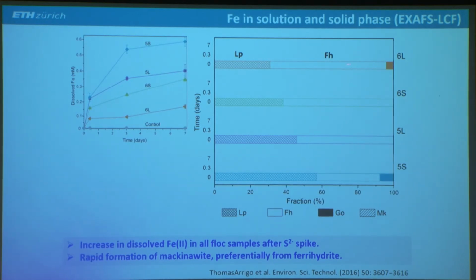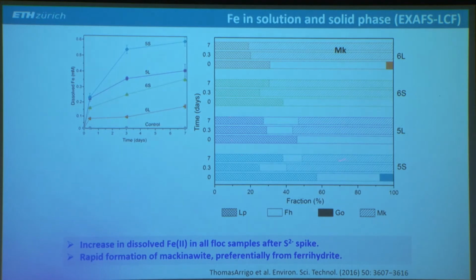Again, some lepidocrocite, and the white bars are ferrihydrite for the 4 different flock samples. And if they are spiked with sulfide and incubated for 0.3 and 7 days, we see a completely different iron speciation. And we see mainly formation of mackinawite at the expense of ferrihydrite. So in the top two flock samples, we didn't detect any ferrihydrite with XAFS anymore, and only mackinawite and lepidocrocite. So it seems like the ferrihydrite was completely transformed to mackinawite. And in the lower two samples, this conversion was not complete. There was still some ferrihydrite left.